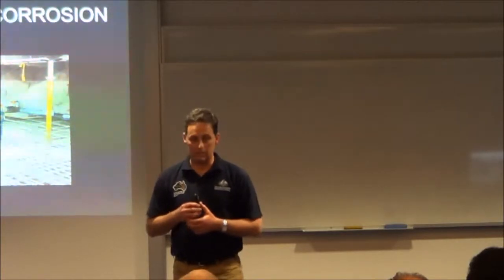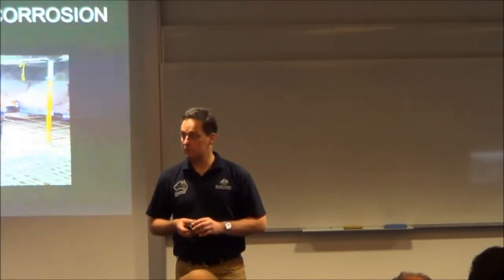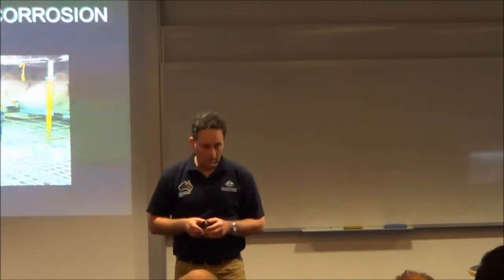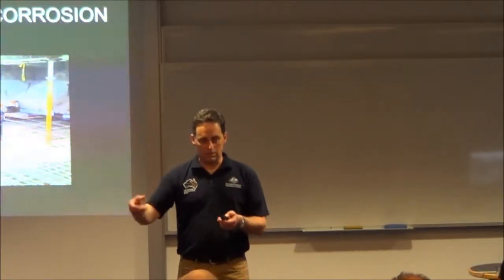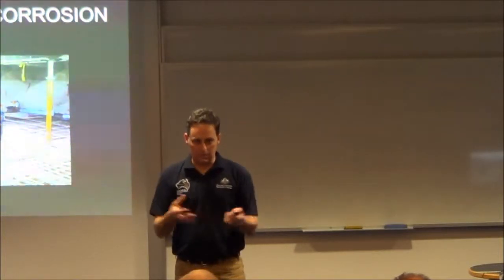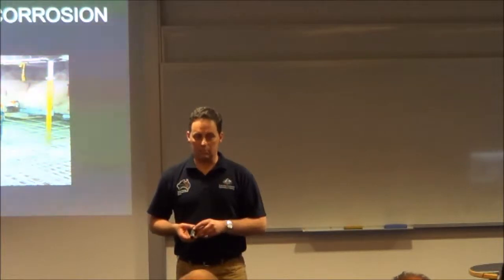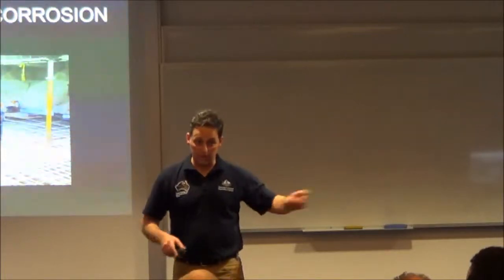My suspicions are that they're probably seeking to produce a decent quality rebar first, making that most applicable. Because it is the glass that breaks down in polymers. So with GFRP pipes, certainly the big problem is exposing glass because it does break down. It's subject to chemical attack. Correct. So the voids therefore allow material to ingress into it. The voids allow contact with the bit that's actually providing most of the tensile strength of the bar. And if the quality of the bar doesn't allow for minimising that, you're going to get some attack. Now, there needs to be quality assurance with the bar that you get, and both those two bars are well quality assured, and so is Fibre.